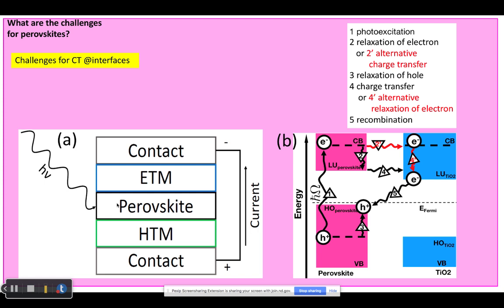But this research has several fundamental and practical challenges. So the figure on the right is focused on this perovskite and ETM layers, and the main question in this design of interfaces is the correct alignment of energies of bands. Because in order to drive charge carriers through the interface, one needs to have a difference of potentials, an electrostatic force, and the difference of potentials is related to energies of LUMO in one and another material if it is for electron transfer, and energy of HOMO in one and another material if it is hole transfer.